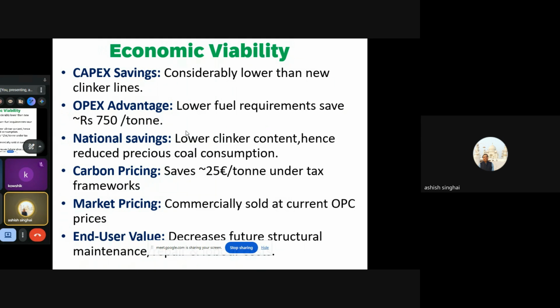End user value, it decreases future structural maintenance and repair costs, and labor component. If the cement is generating a huge amount of heat of hydration, possibly cracks will appear more often than not, and later on the end user has to undergo a lot of repairs, maintenance, and all those costs. But in case of this particular cement, which is densely packed and cohesive in nature, it will not generate that, and at the same time the carbon dioxide emission is very, very low, with lower heat of hydration, so it will produce a cement which will not generate cracks to the extent other prevalent cements are generating. So there can be a lot of saving for the end user as well.